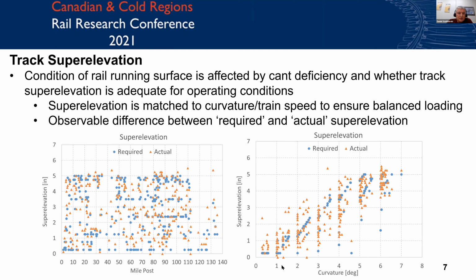And on the left hand side, you see this point cloud essentially of the super elevation for the required numbers and for the actual numbers, and it doesn't look like much. But when you organize that information in the curvature domain, the picture becomes much more clear. Essentially, as the curvature starts increasing to 1 degree, 2 degree, 3 and 4 and so on, that super elevation difference starts getting more and more positive, meaning that the cant deficiency starts getting bigger. The problem here is that yes, the trend is good, but the required numbers don't quite line up with the actual numbers, right? They seem to be sort of the same trend, but they're not exact.